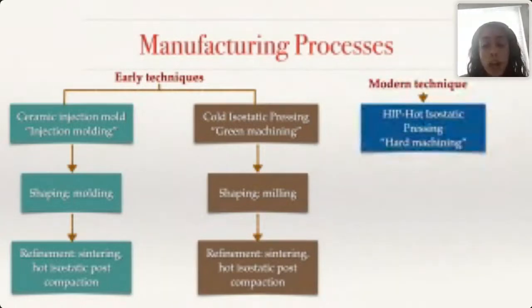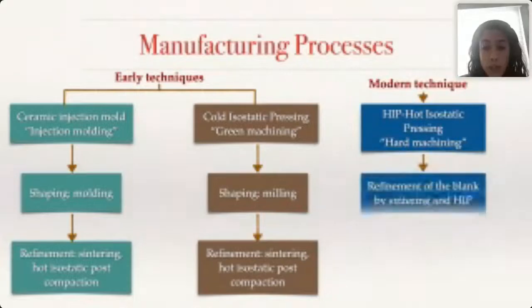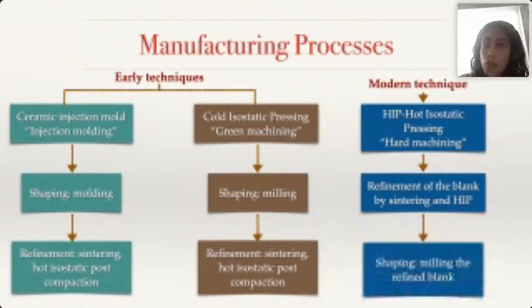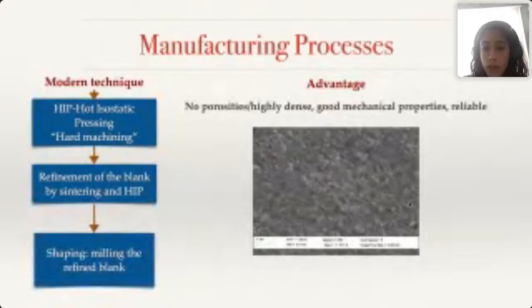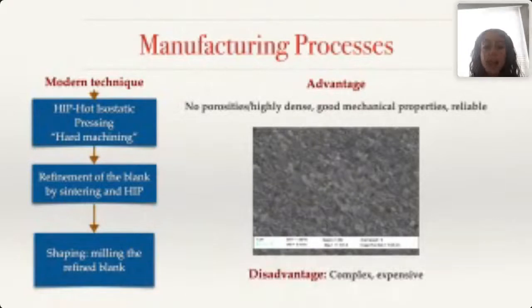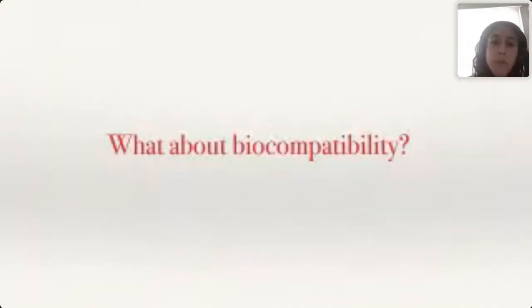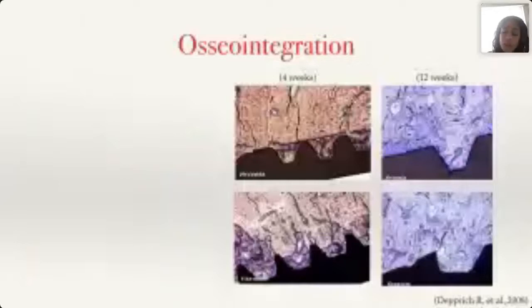The best technique to use is hot isostatic pressing, or hot hard machining. With this technique, the grains are pressed together to ensure there is no porosity within the material, so the mechanical properties are very high because we get a very dense material. This is a sample from one of the groups I tested during my studies in France - this is the Straumann group. You can see it's very well compacted with no porosities inside. The disadvantage of this technique is it's complex and expensive, so it's not very cost effective, but it does provide the best material.